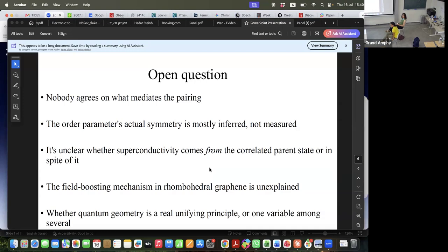And that also happens in this experiment of Nadj-Perge that pushes the system to have spin orbit coupling. He uses a substrate, I forgot the material now, but there was a TMD with spin orbit coupling. Then when you push the electron wave function to the TMD, suddenly there is superconductivity. So the idea was that it's the same kind of mechanism.